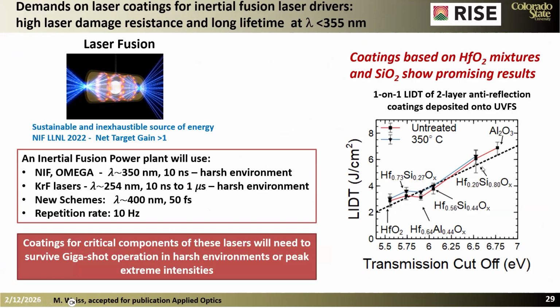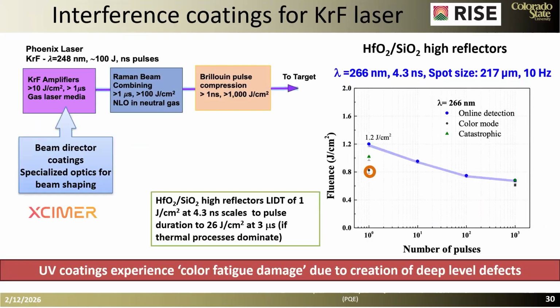What we showed is that going with mixtures allows us to achieve very high laser damage thresholds in anti-reflection coatings, which are very challenging because they are the lowest laser damage threshold component, of the order of 6 joules per square centimeter. Here, the pulse duration is of the order of 10 nanoseconds. In support of the Xcimer Energy approach, the coatings will go into the amplifier, and there will be some coatings on the windows of the Raman cell and the Brillouin cell, at least at the entrance window.